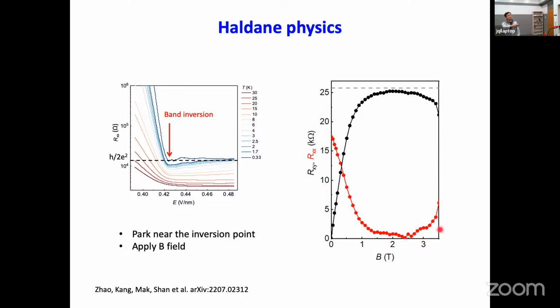We try to keep at the band inversion point here because the gap is closest to the critical point. The gap is the smallest. And then we look at how the Hall resistance and the longitudinal resistance depend on the magnetic field. You can see that once we turn on the magnetic field at around 1 Tesla, our R_xx already dropped to a very small value. And then the Hall resistance goes up very quickly and finally reaches about the quantized level at about 1.5 Tesla of magnetic field. And so that's consistent with this picture that you split the copy of the Kane-Mele quantum spin Hall insulator into a Haldane-Chern insulator by breaking the time reversal symmetry in the system.